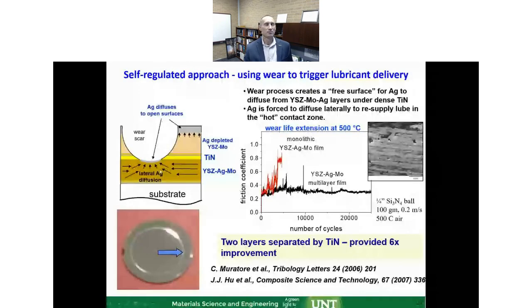The problem with that mechanism is that it's diffusing sometimes too fast, especially as you start increasing temperature, say to 500 C. The diffusion is so fast that all the material gets depleted very quickly from the surface. So one of the ways to address that is to put in a diffusion barrier layer, such as titanium nitride, and it will restrict the diffusion. Just by putting in a titanium nitride diffusion barrier layer and doing nothing more, we have an extension of the wear life for many thousands more sliding cycles, because it restricts the diffusion towards just the wear track, which is needed, using a subsurface diffusion mechanism here.